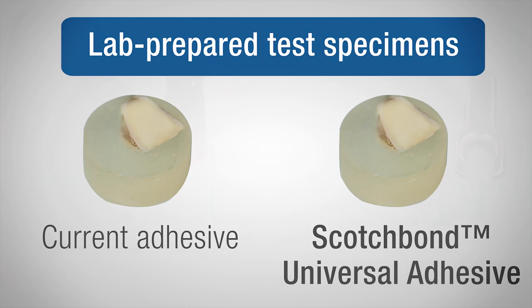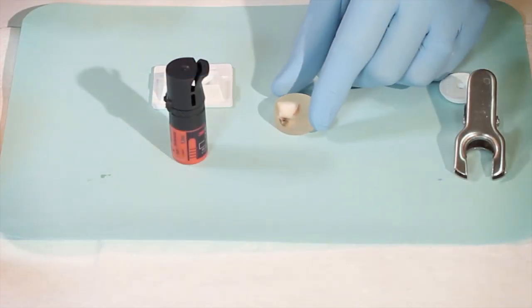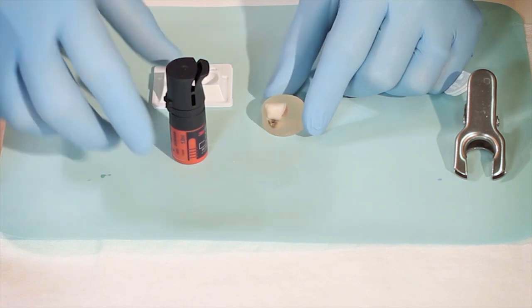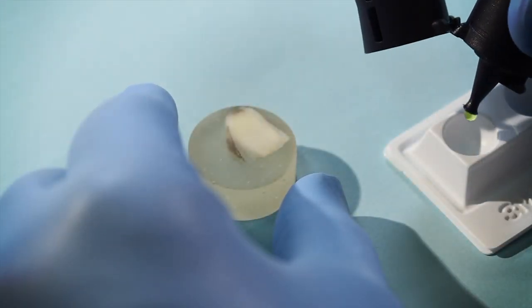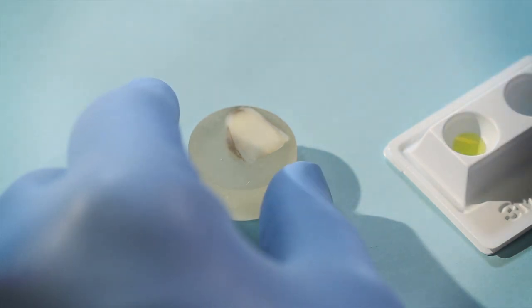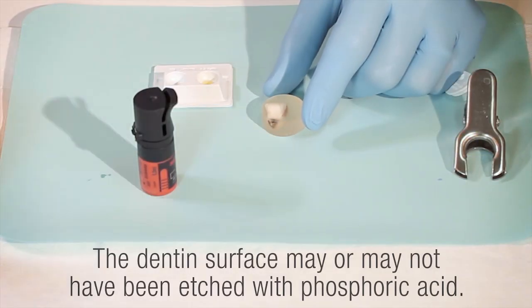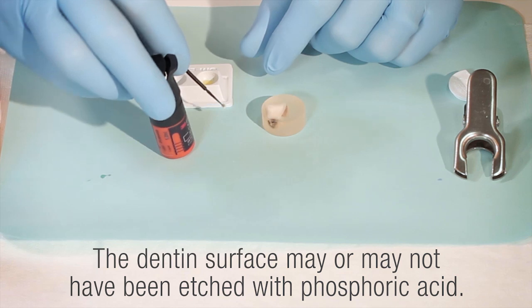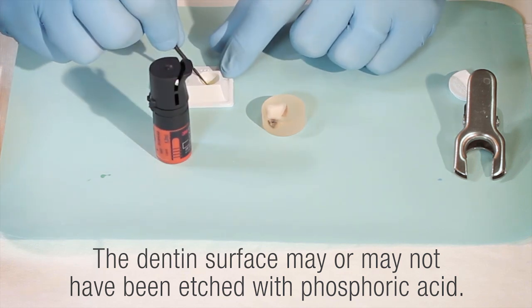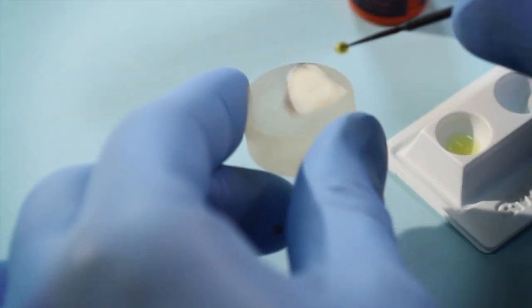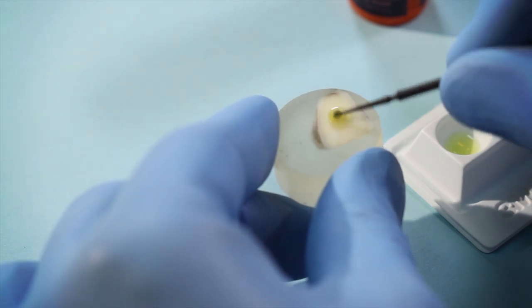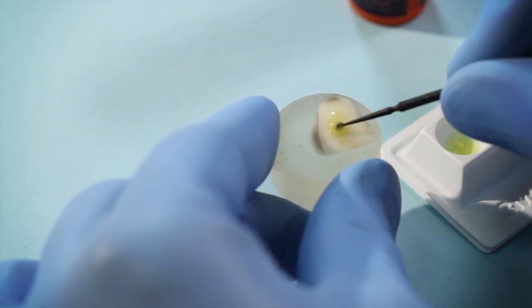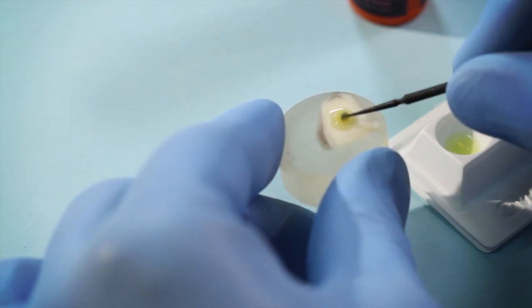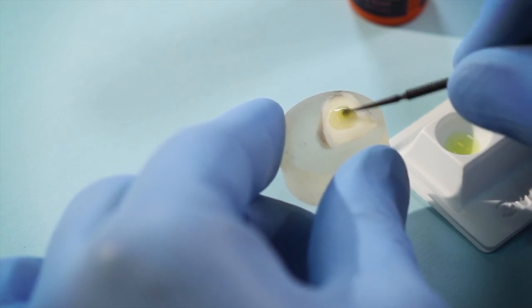To create the test samples, dentists first applied the adhesives to the exposed dentin surface, following the manufacturer's instructions for use. With Scotchbond Universal Adhesive, the dentin surface may or may not have been etched with phosphoric acid, depending on the dentist's preference. Scotchbond Universal Adhesive was then applied with a brush using a scrubbing motion for 20 seconds to assure uniform distribution across the surface and penetration down into the dentin.